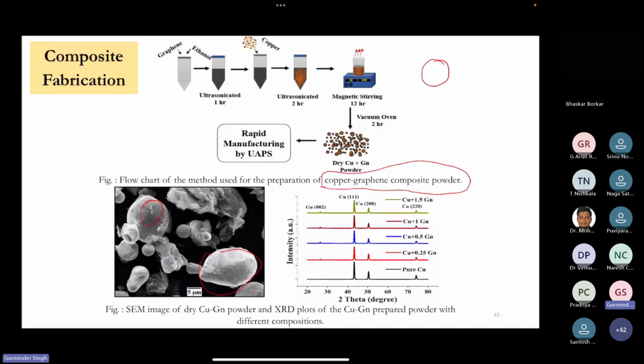So instead of using ball milling, we used ultrasonication for a longer time, where we mixed the graphene in ethanol, and later on we put in copper and mixed it for longer hours in an open magnetic stirrer, so that the ethanol can easily evaporate and the copper gains an addition of graphene. Like you can see, this is graphene adhered on the copper particles, and you're getting spherical particles with a similar shape to before starting the mixing process.